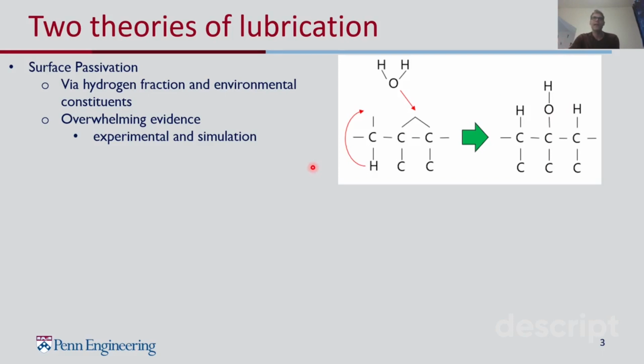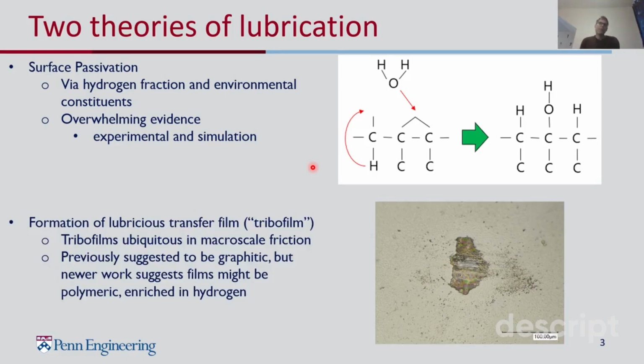across the interface. The evidence for this mechanism being important is really overwhelming. There's a lot of it, both experimental and simulation, showing that this is a necessary condition for low friction in these systems. The other one is the formation of a transfer film, which we refer to as a tribofilm. And so basically how this happens is some of the diamond-like carbon actually gets transferred to the counterface. So then you have this film sliding against the diamond-like carbon.